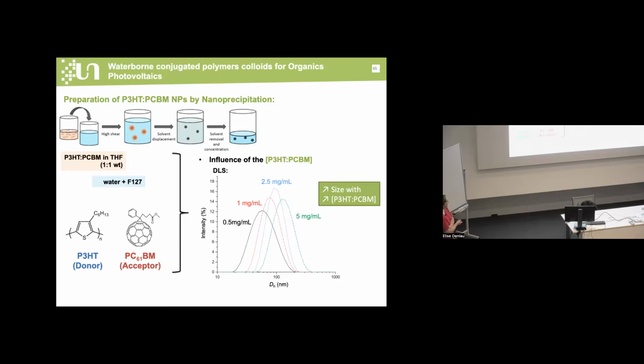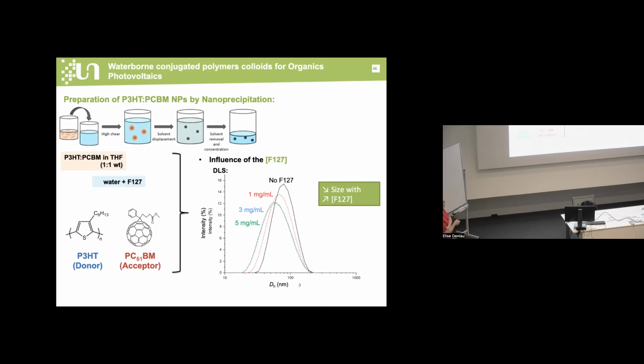monodispersed. And we check the influence of the concentration of active material on the size, and you can see that the size of the nanoparticles increases with increasing active material concentration, but we keep a range of about 100 nanometer nanoparticles. Then we also check the influence of the concentration of surfactant, and we could see that the size of the nanoparticles decreases with increasing concentration of surfactant, which is quite intuitive. But again, you can see that the shift in size is not very extraordinary.